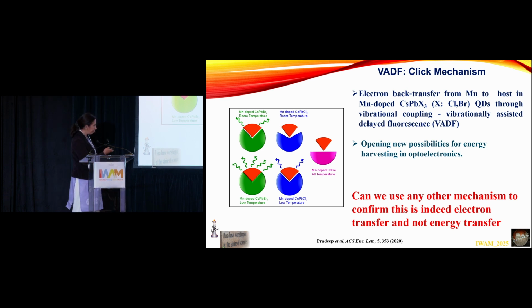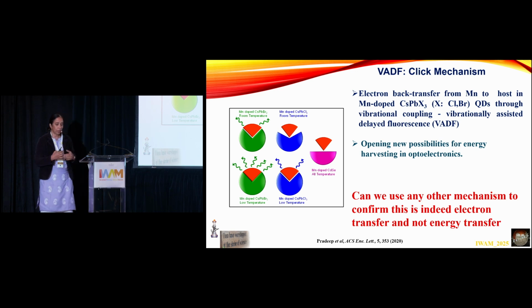And for the chloride, it is not so well matched, but still matched good enough for me to have the transfer, especially at lower temperatures. And for the II-VI semiconductors, there is no interaction with the manganese. So now the big question is, I have been talking about this transfer as a charge transfer. I have not specifically shown that; it could very well be an energy transfer as well.